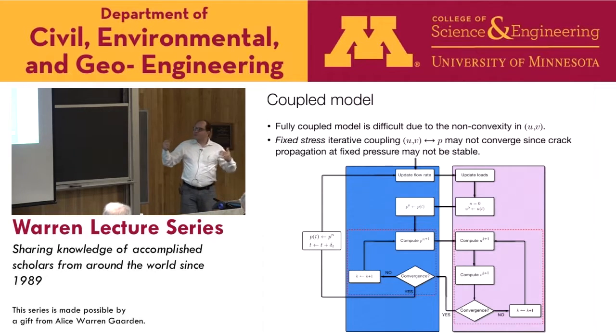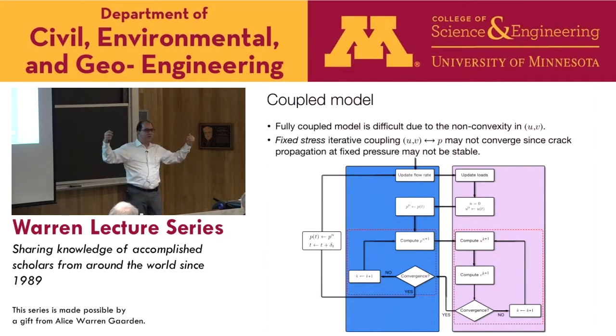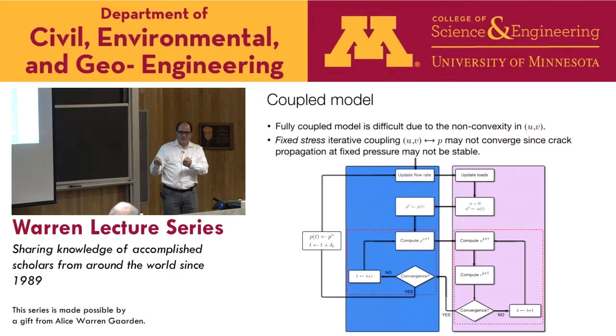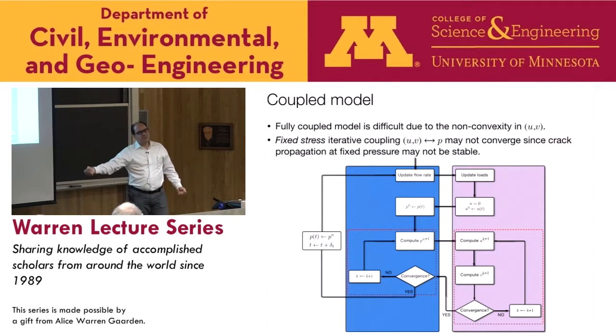And the reason is actually why I presented the Sneddon problem. Of course it does not work, because we know that if we fix the pressure, even in this really simple problem of the Sneddon crack, you compute a fracture pressure, and then you try to compute the equilibrium displacement plus crack. There is no such thing as the displacement plus fractured equilibrium. Formally, if you want to prove convergence of an iterative coupling, you need some kind of a contraction map. You need to show that a small change in pressure leads to a small change in displacement, and a small change in displacement leads to a small change in fracture, so there is a chance that it converges. Here, this is not the case. A small change in pressure can lead to a very large change in displacement plus crack. So there is no way this type of coupling is going to work.